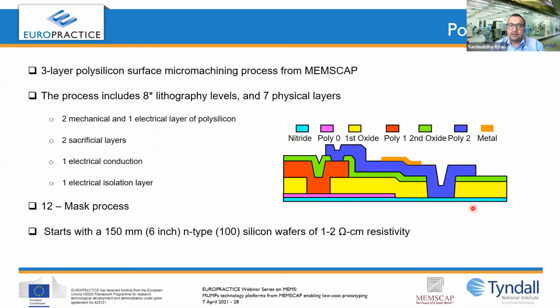and it involves a lot of lithography levels, that is 8 lithography levels and 7 physical layers. Out of those 7 physical layers, there are 3 polysilicon layers, 2 oxide layers, 1 metal layer, and 1 nitride layer. The poly 1 and poly 2 layers can be used as the mechanical layers. One poly layer, poly 0, is used as an electrical layer for making electrical connections. The metal layer is for probing the devices or for packaging, so for bond pads and everything. They are called electrical conduction layers, and there is 1 electrical isolation layer, that is the nitride layer. The first oxide and second oxide are basically sacrificial layers.